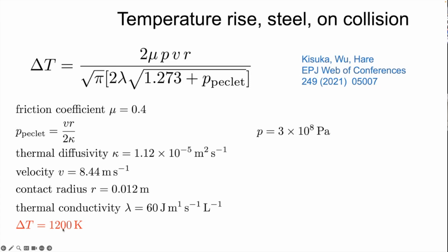That comes to a very impressive 1200 Kelvin momentary temperature rise, which is far greater than the spontaneous ignition temperature of jet fuel. So even if my calculation is wrong by 500 degrees centigrade, the jet fuel will definitely ignite, and that is the reason why we had the fires. And because the fuel spilled onto both ships as a consequence of the impact, both ships were on fire and were abandoned quickly, although there was one tragic loss of life.